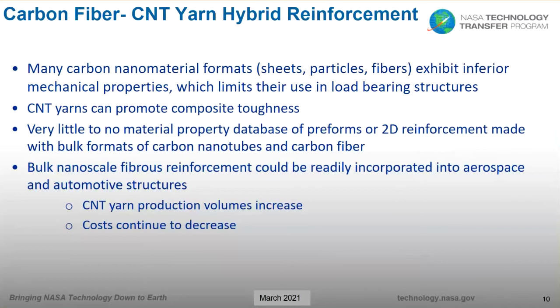But instead of trying to use a fully nanocomposite material for a load-bearing application, there are some advantages to making a hybrid from a carbon fiber, more specifically carbon nanotube yarn combination. For one, the carbon nanotubes that we used were very tough and not very susceptible to damage. So the role of the carbon nanotube yarn in this hybrid would be the constituent to introduce toughness.